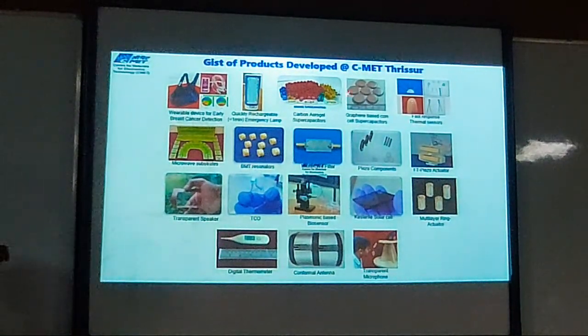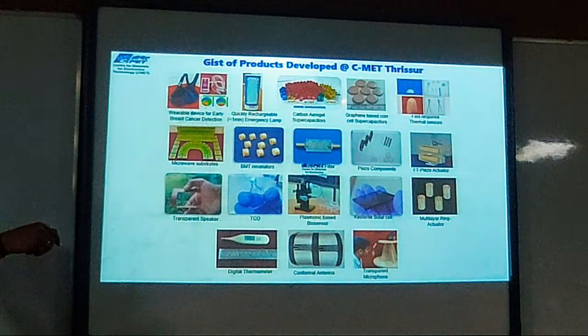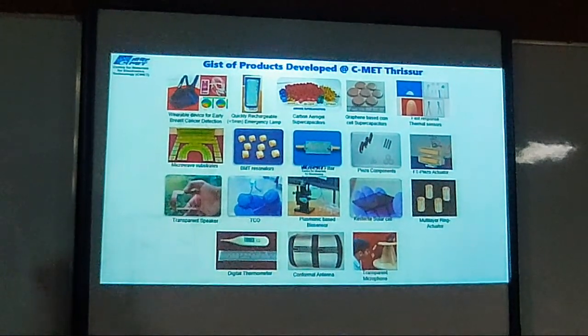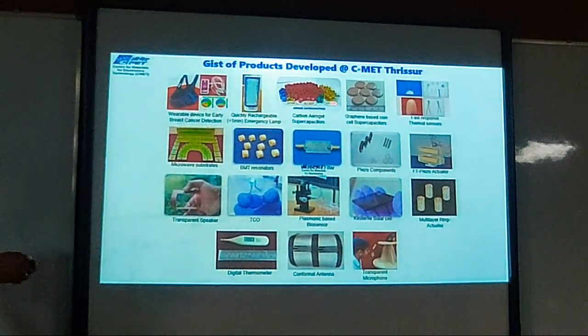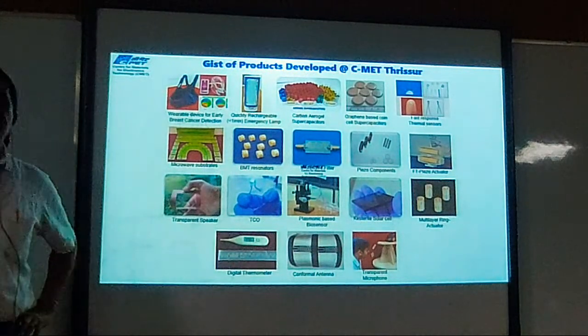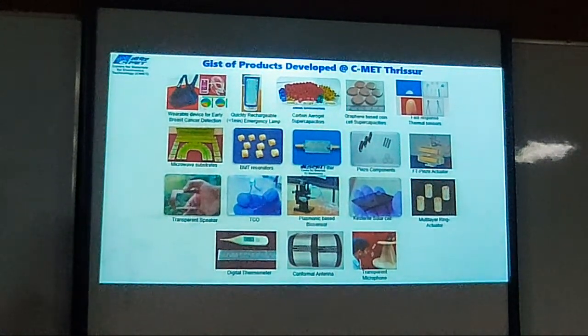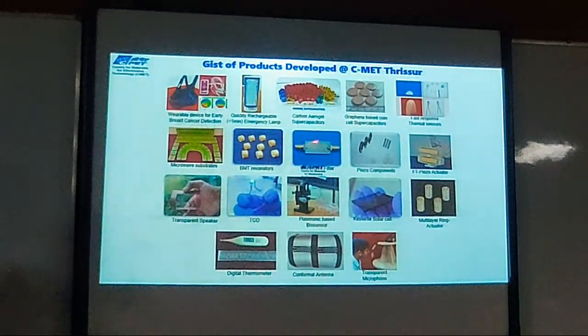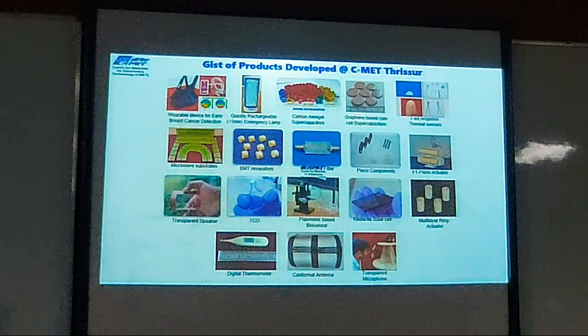Then we have a supercapacitor. So we can make supercapacitor from 220 farad to 500 farads, and this technology is ready. So what is the beauty of that? We have the carbon aerogel production facility, because carbon aerogels are required in the supercapacitor. In supercapacitor, the major material uses carbon, which should have the surface area almost more than 1,000 meters squared per gram. So we are doing that.